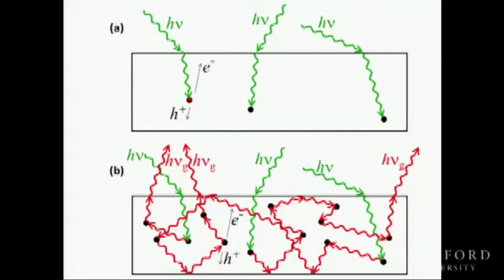Of course, the photons come in, the green photons come in, they get absorbed, et cetera. But you also have, accompanying this, a tremendous amount of fluorescence. And it has to be very, very high because only 2% of it is able to escape. So this is bandgap luminescence or fluorescence. And what it says is that the new physics is shown in part B here, that yes, you have your incoming photons get absorbed, but accompanying that, inside the solar cell, there should be a tremendous photon gas representing as much as 50 suns of internal fluorescence, trapped and some of it escaping. So that represents the physical situation.